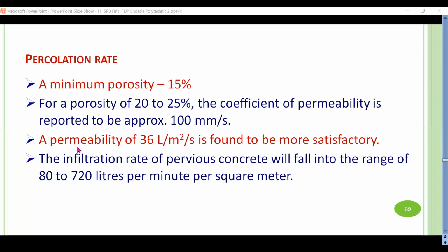So, a permeability of 36 liters per square meter per second is found to be more satisfactory. The infiltration rate of pervious concrete will fall into the range of 80 liters per minute per square meter to 720 liters per minute per square meter. So you can see a very huge quantity of water will percolate through this pervious concrete, and it will help in saving our environment. It will help in recharging the groundwater level. It will help in reducing the pollutants from the runoff water. So all these advantages are there.